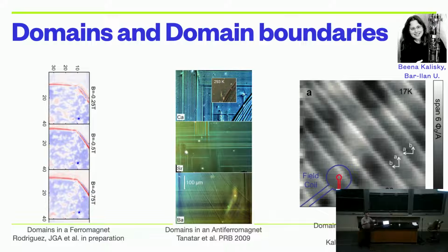So you can imagine having a slab of material, and then you're taking your SQUID tip and actually measuring where it's superconducting and where it isn't superconducting as you go across. And what she saw was that you got stripes of superconductivity right along the domain boundaries. And I was really curious about this, because what it was showing was that while you're getting superconductivity at the domain walls, like between those different directions of the antiferromagnet or the different directions of the nematic order, you actually got more superconductivity than before.